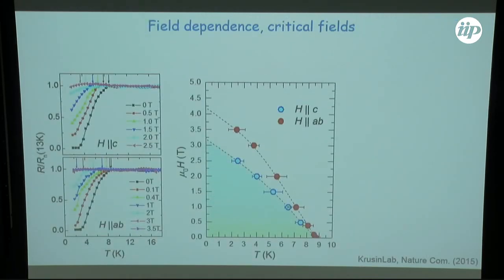The field dependence is also very peculiar. At first, you look at this field dependence, and this is just a resistive critical field or a limiting field. TC is around 9. This is not remarkably high, but what you see here is that the anisotropy is very low. This was surprising at first, because the structural anisotropy is huge. The C-axis parameter is 30, and the AB plane is less than 4.